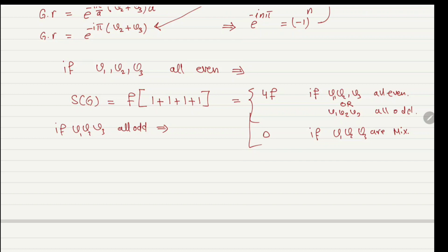In summary, if we have the 2, 0, 2 plane, you will see a diffraction profile for the plane 2, 0, 2, and you will see a diffraction profile for 1, 1, 1, and you will see a diffraction profile for 3, 1, 1, but you will never see a diffraction profile for 2, 1, 0 or 1, 0, 1 or 3, 0, 1.